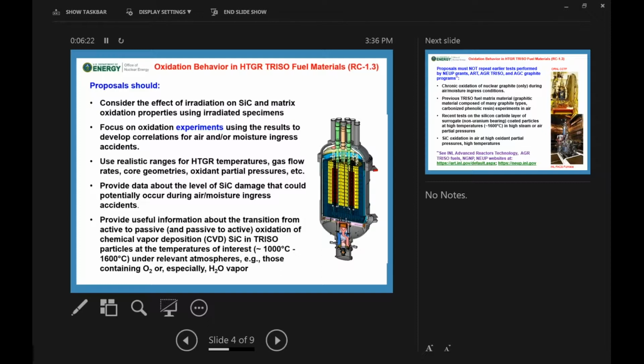So we want you to have proposals that consider the effect of irradiated silicon carbide and matrix properties to use as specimens. We want you to focus, of course, on experiments. We want you to use realistic ranges for the gas-cooled reactor, gas flows, and things like that. We want you to provide data about the level of the silicon carbide layer damage that could happen during an